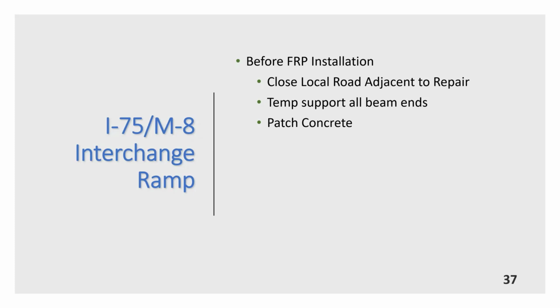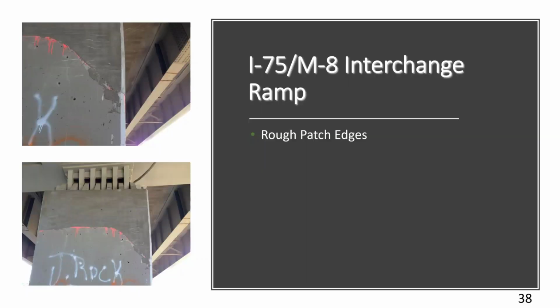Hit the fast forward button here. You can see that the concrete is patched. And what I'd like you to notice here is that the edges of the concrete patches are pretty rough and irregular. And also that we didn't use any special patching concrete. We just used the standard 4,500 PSI mix that MDOT specs out.